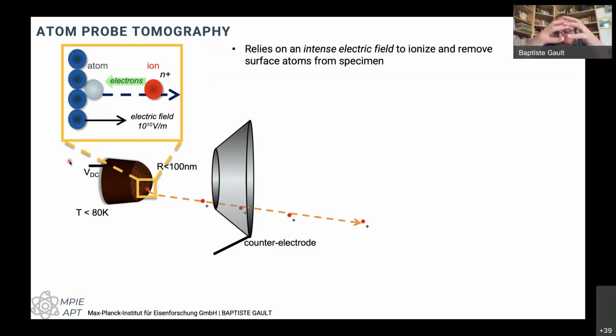So you apply a voltage, the field will distribute across the entire chamber. So depending on the position, for example, of this counter electrode with respect to the specimen, you will have a distribution of the field that is modified. These days, we typically have only about 40 microns distance here, and we can address one of these specimens, just one, even though we can prepare multiple on this support that I've shown you before.